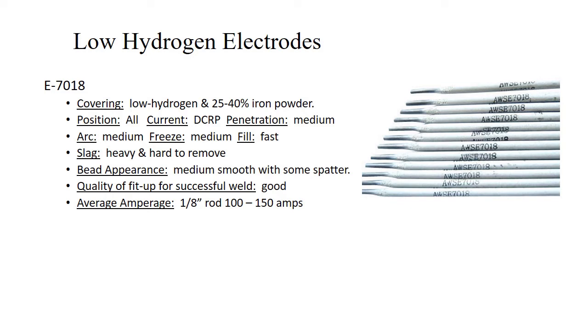And your average amperage for an 1/8 inch rod, you're going to run it a little hotter than you're going to run 6010. You're going to run it at about 100 to 150 amps to really have some success with it. But the difference between this and 6010 is, with 6010, the flux is wood chip and paper. It's going to burn. With this stuff, you're melting iron, and there's some other ingredients in that flux that are mineral based, and you're basically having to melt those. Whereas 6010, you're just burning it. This, you're melting it. So it's going to take more energy to melt than it is to burn. That's why, even though it's an 1/8 inch rod, you're still going to have to run it at a much higher amperage than you would a fast fill electrode like a 6010 that's got a cellulose covering.